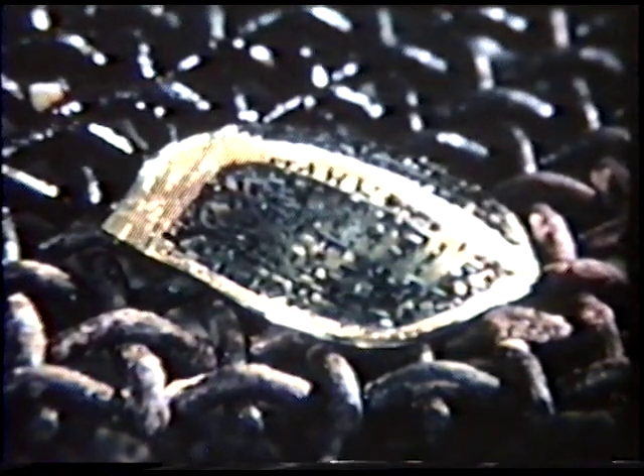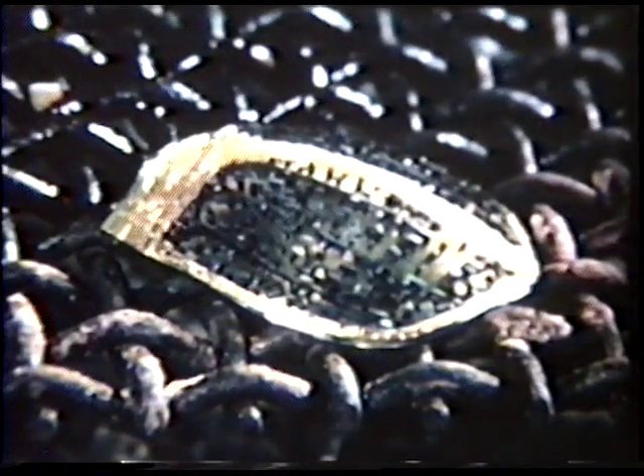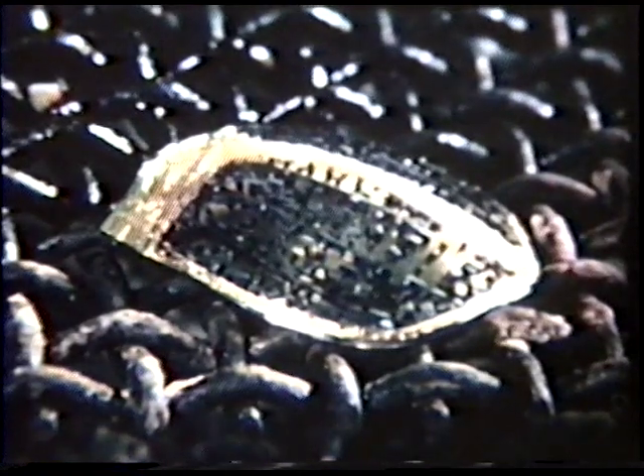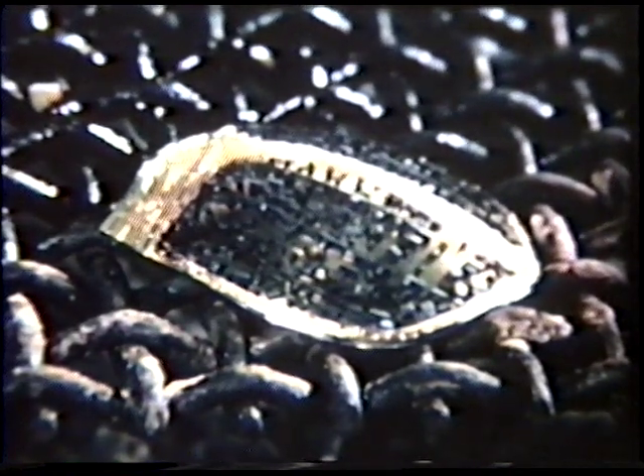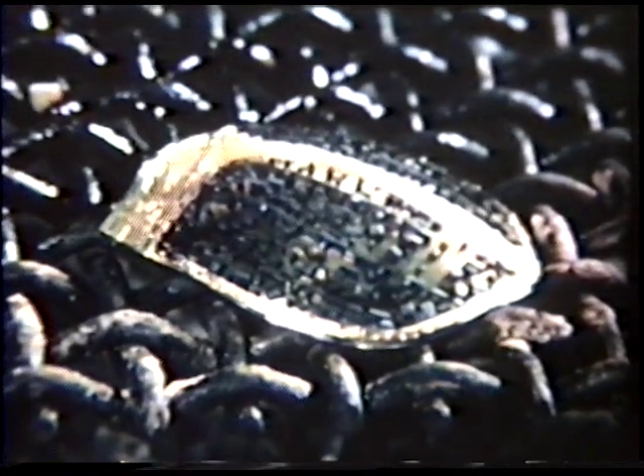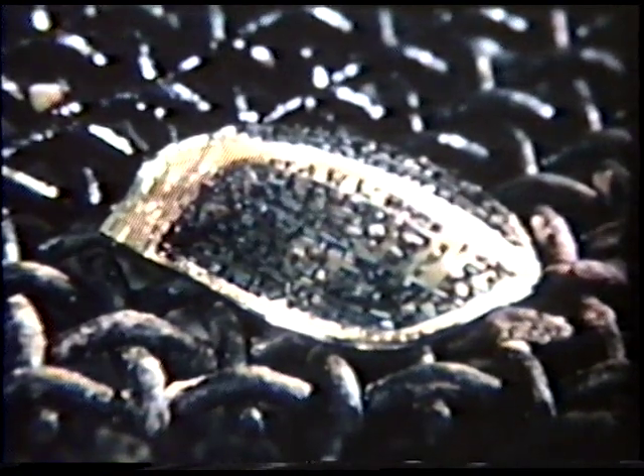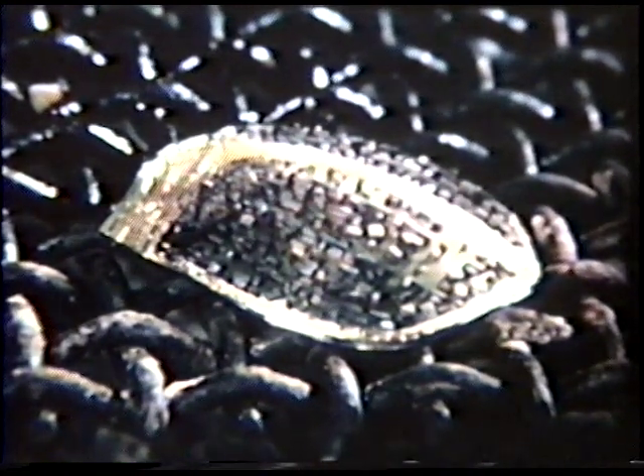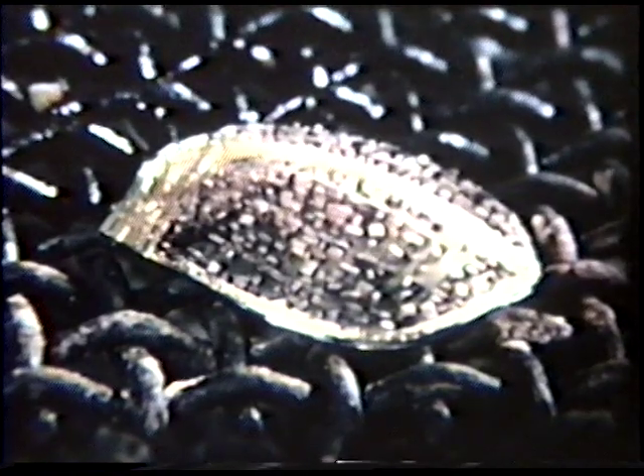The effect of the flame is first seen as the tragacanth darkens and becomes carbon. In parts of this sequence, the changes are speeded up as the camera was run at 1/3 normal speed. Gradually, the rectangles change from black to copper color, and finally the surface of the rectangles glistens as the copper unites with the gold and forms a film of liquid solder on the surface. This film of solder flows into the joint and bonds the pieces together.